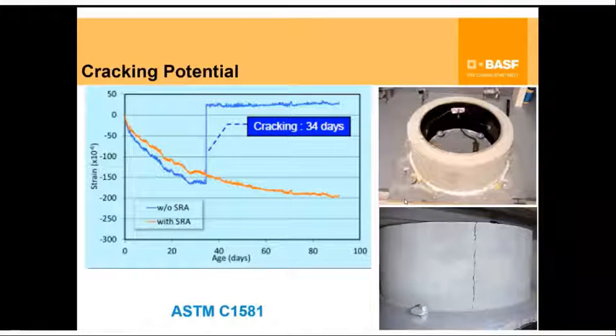The cracking potential can also be measured using ASTM C1581, which is basically also called the ring test. So you have a ring which is under stress because of the metal piece inside, and then you're measuring the strain over time under constant humidity and temperature conditions, looking for the propensity for the particular concrete material or design to crack. And the blue line that you see is the release of the strain. So as soon as the concrete cracks, it's actually a stress release mechanism, and you will immediately see the release in terms of the blue line.